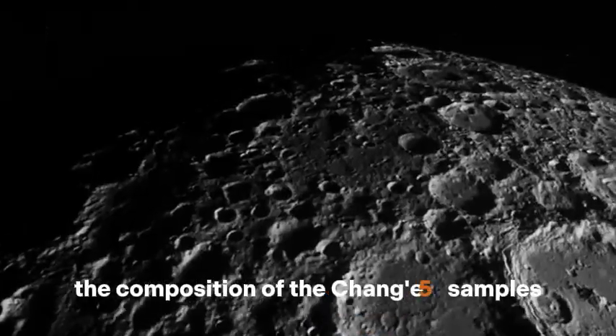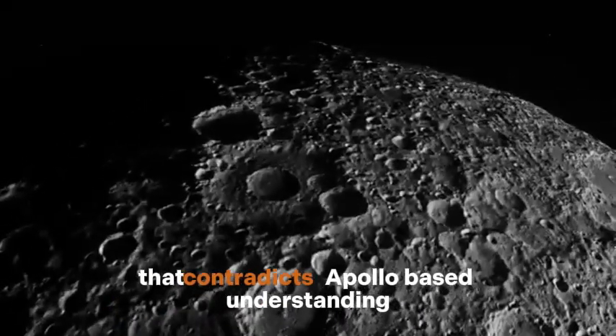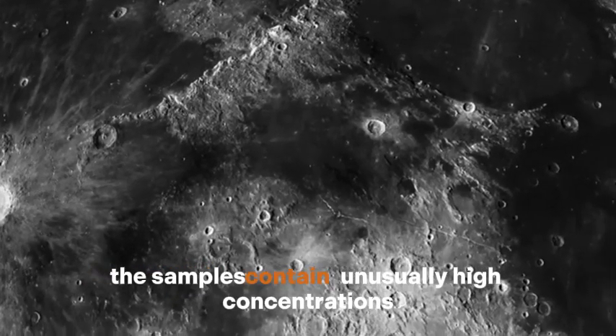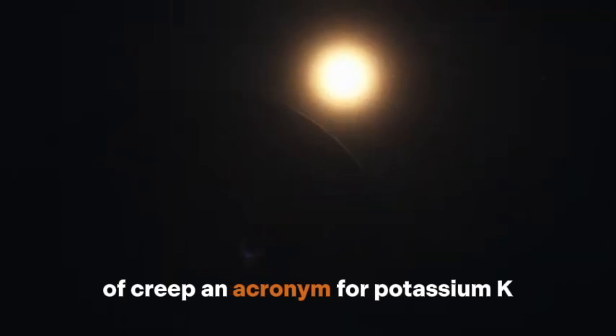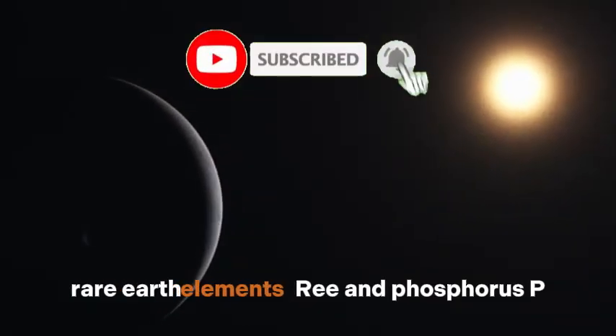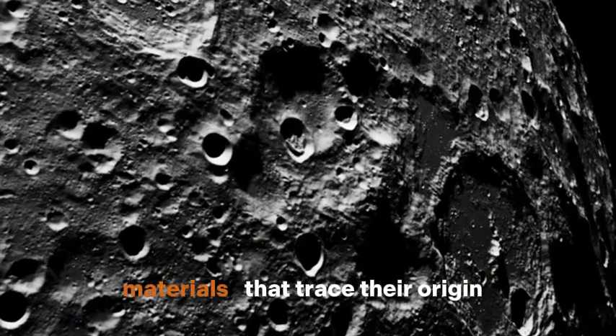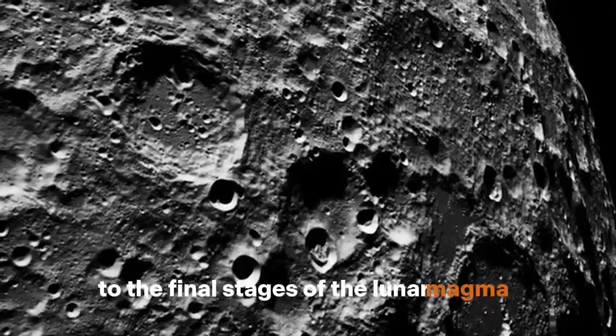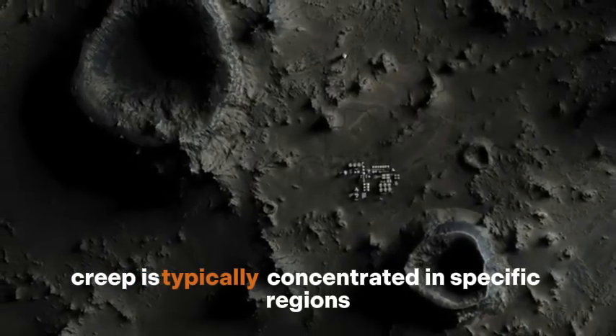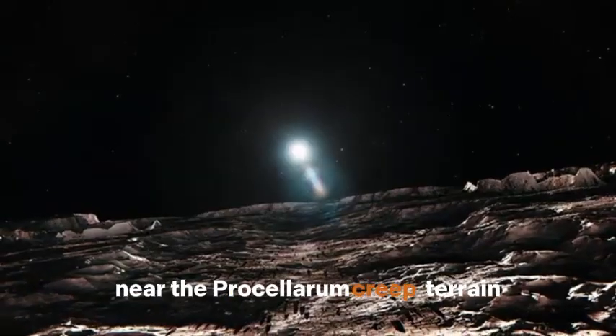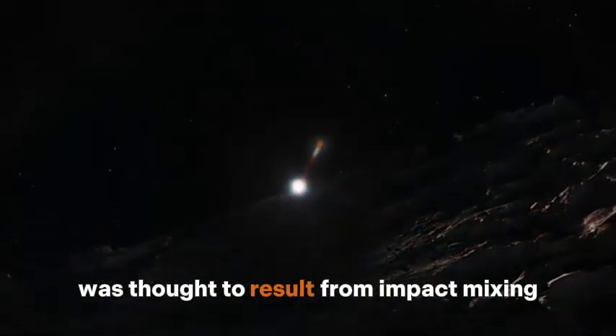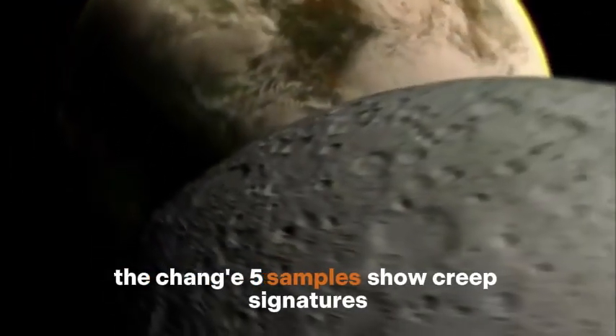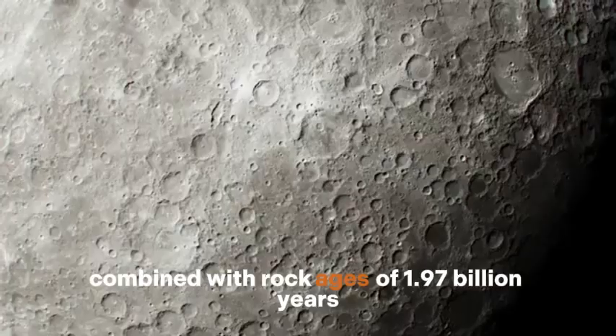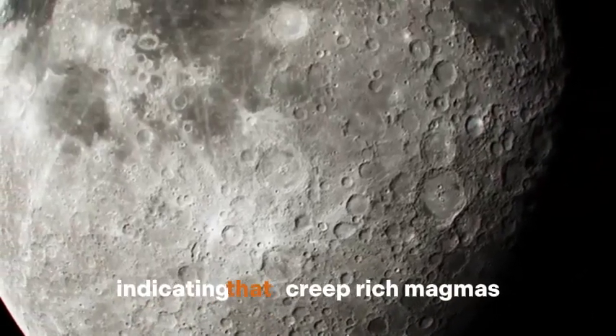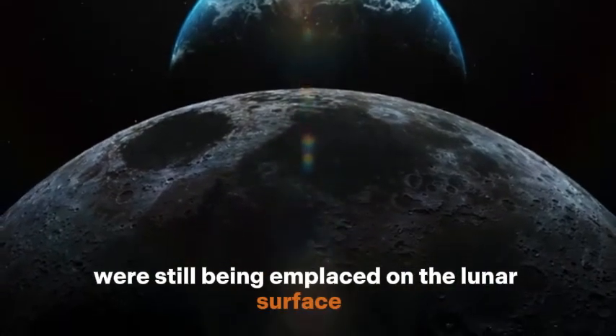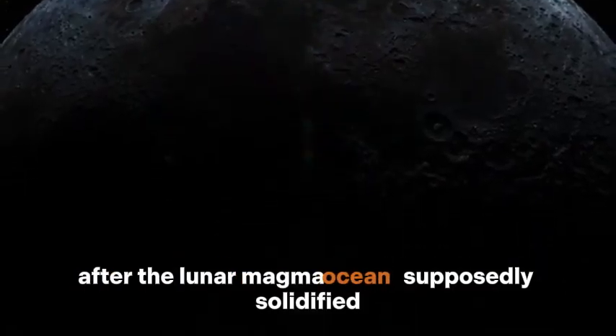The composition of the Chang'e 5 samples revealed another surprise that contradicts Apollo-based understanding. The samples contain unusually high concentrations of KREEP, an acronym for potassium, K, rare earth elements, REE, and phosphorus, P, materials that trace their origin to the final stages of the lunar magma ocean's crystallization. KREEP is typically concentrated in specific regions near the Procellarum KREEP terrain, and its presence elsewhere was thought to result from impact mixing. The Chang'e 5 samples show KREEP signatures combined with rock ages of 1.97 billion years, indicating that KREEP-rich magmas were still being emplaced on the lunar surface nearly 2 billion years after the lunar magma ocean supposedly